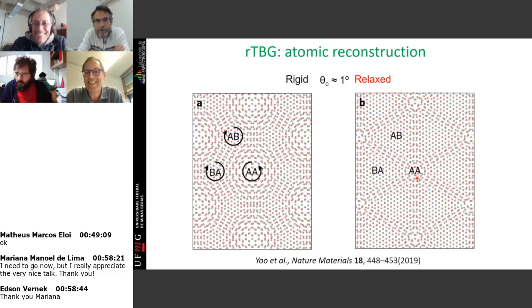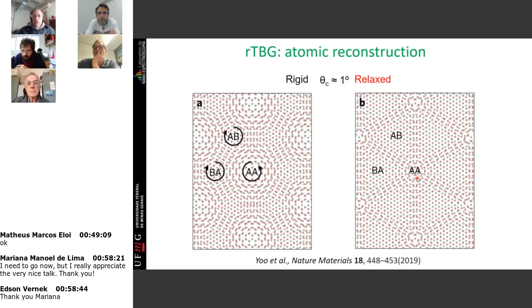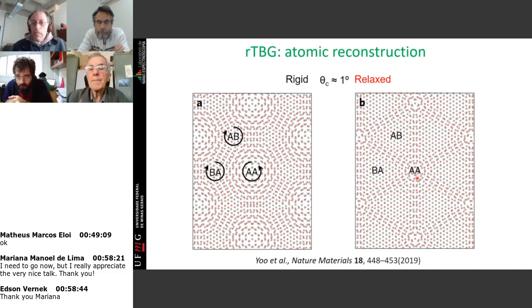Sure, you made a comment about finding strong electron-phonon interaction exactly in the places where people have seen superconductivity. I assume that the people who are claiming that this is unconventional superconductivity were not very happy, right? That is so. There are papers in the literature saying that electron-phonon coupling is very strong in this range, so the phonons might play a role. But at the same time, you are right. There are people saying that the superconductivity in this material has nothing to do with phonons. And this information that I add here only confirms that you have strong electron-phonon coupling, but this doesn't mean superconductivity is due to it.